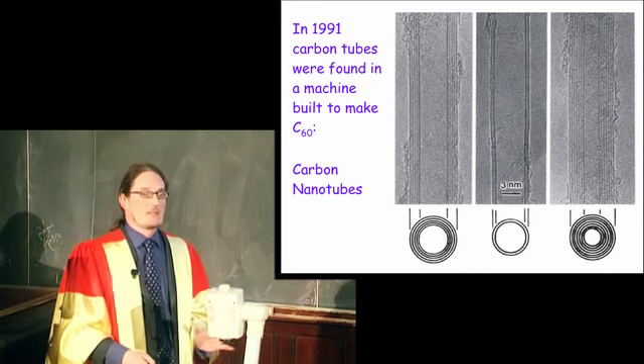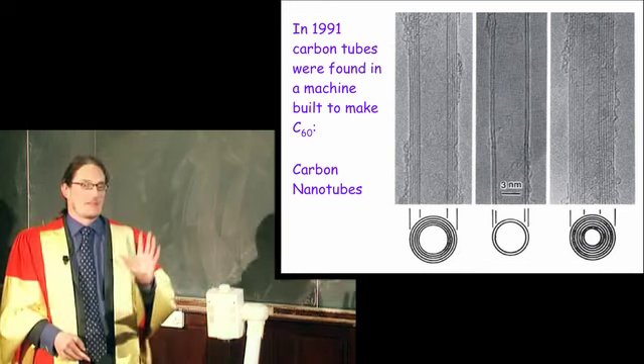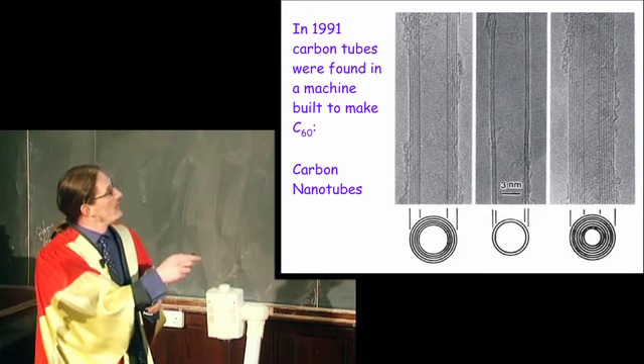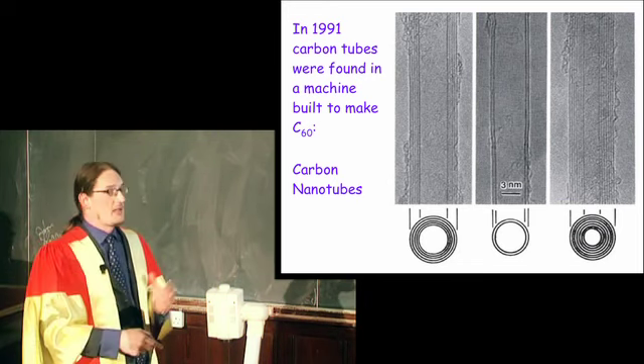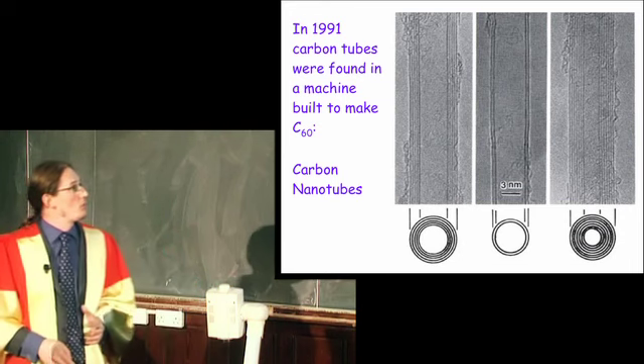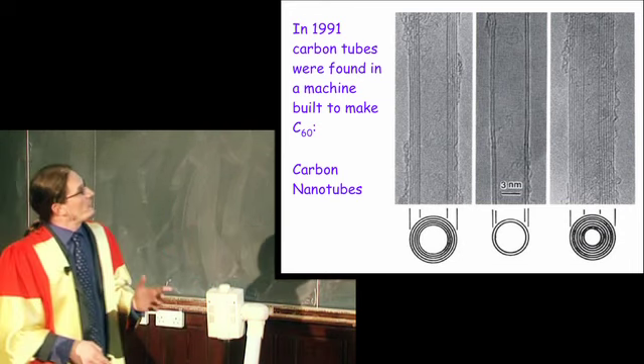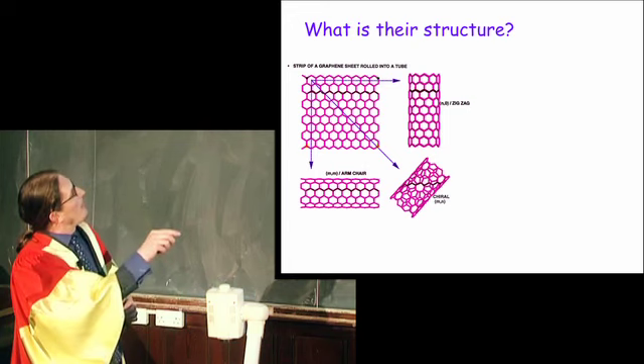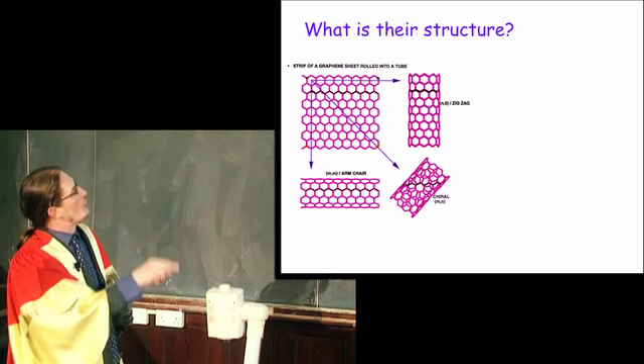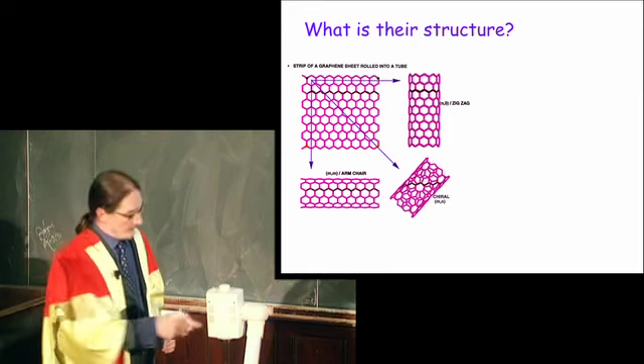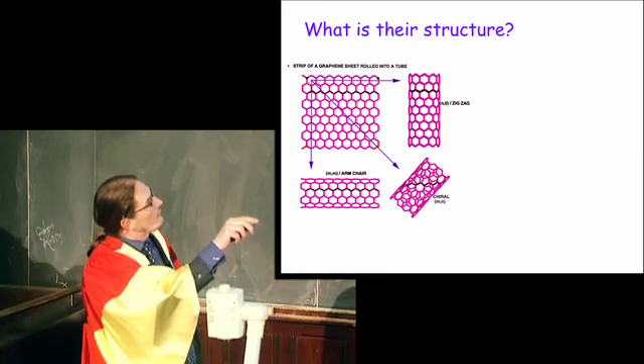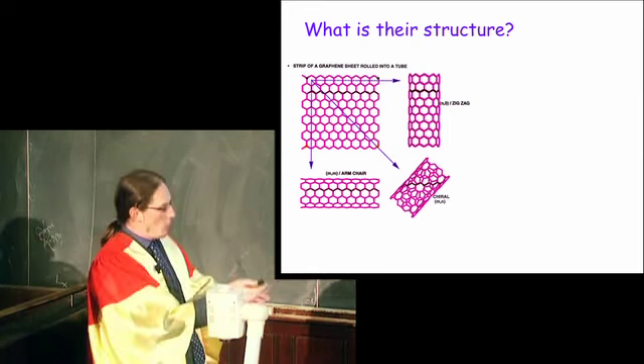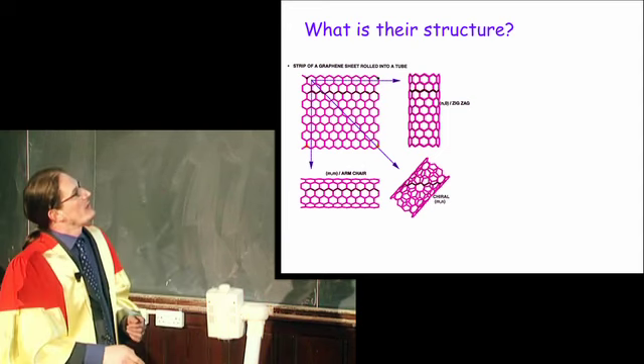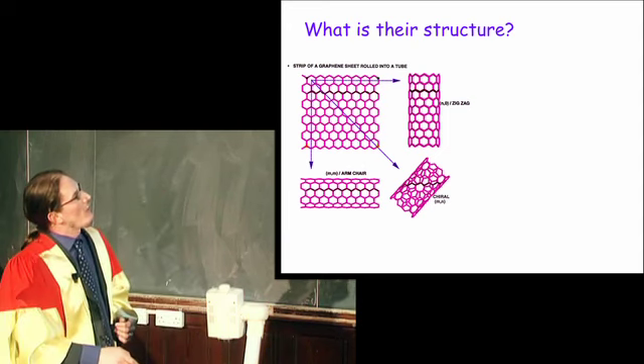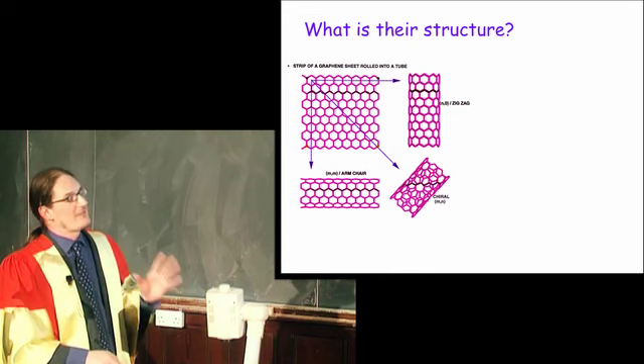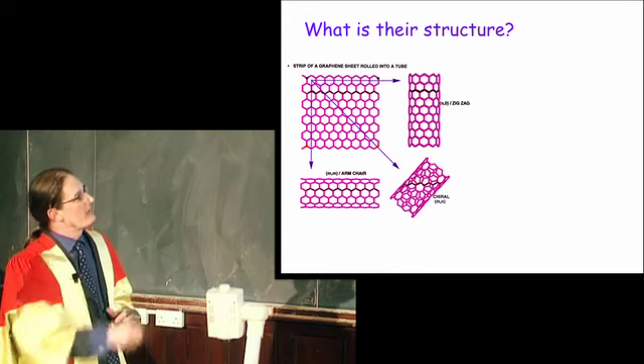And almost immediately, people realized that these things could be useful. They realized that they were somehow related to graphene, they were long, they were thin, and they might be good for something. So what's their structure? Well, you take a piece of graphene and you roll it into a tube. Now, the interesting thing about this is that there isn't just one way you can roll up the tube. You can roll up to form a tube one way, then you can imagine opening it and rolling it back together at a different angle, and you get a slightly different tube.